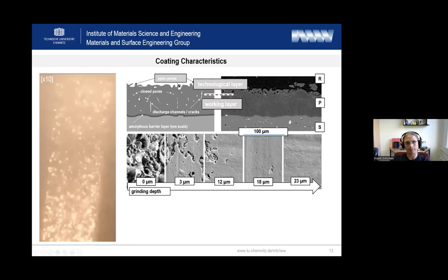And just to show that we have to deal with a really dense oxide morphology, we have here an exemplary series of grinding pictures. We took such a coating and ground it step by step. Firstly, we see an untreated top view, and then we see how the morphology develops if we go 3, 12, 18, and 23 micrometers inside the coating. And we see that we have a really dense oxide morphology.